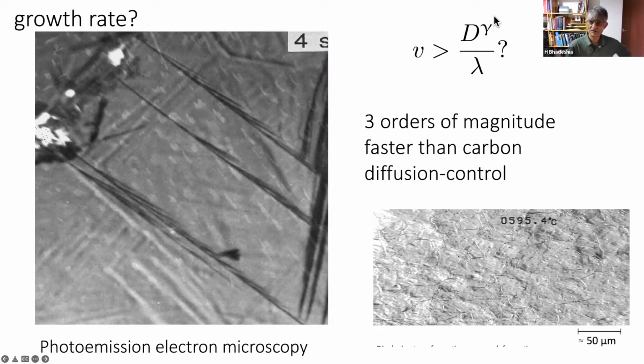And this is the equation that I showed you earlier, but you can use more sophisticated theory to deal with the shape that we have here. And that was developed by Ivantsov and Trivedi and so forth. And show that these plates grow 3 orders of magnitude faster than carbon diffusion can happen. Okay? So you should think of bainite as a completely diffusionless transformation product. So how does it differ from martensite? Well, I'll come to that later.